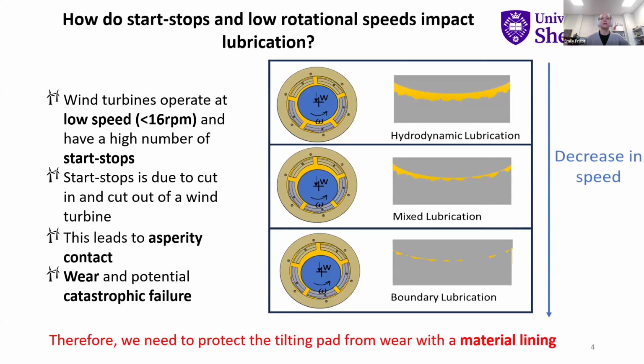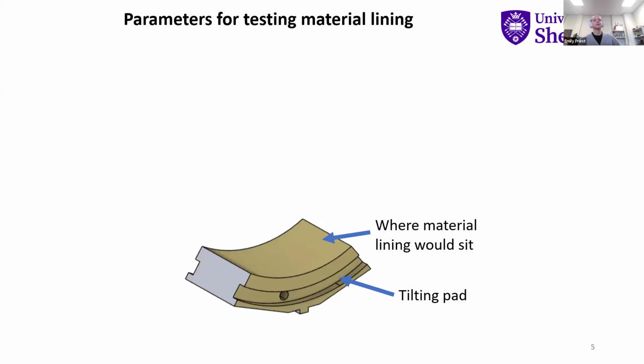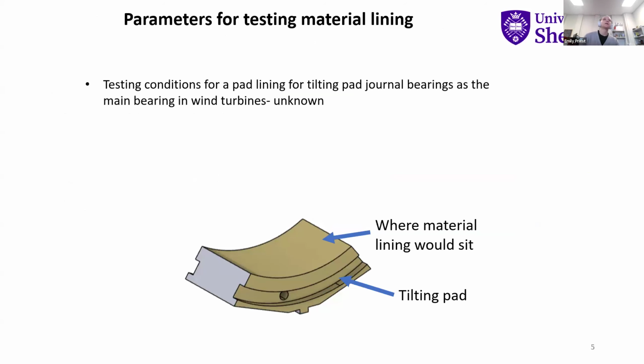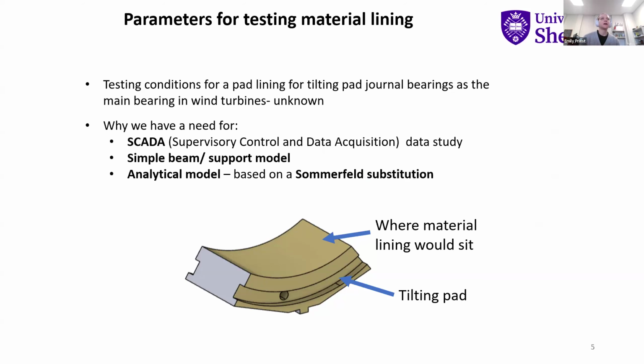So we need to protect the bearing from wear, and we do that by using a lining material, which would sit here on the tilting pad. But the issue with conducting tribological testing on this material layer is that we don't know the testing conditions, like the loading or the lubrication conditions.